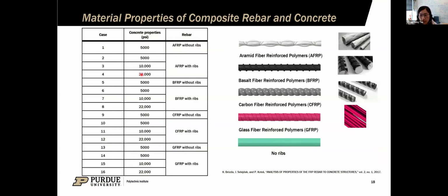So the data provided by the physical testing is limited because it takes quite a long time to do each sample experiment. So we want to use a large data set for optimization and condition assessment. We definitely need some complementary ways to generate the data. So here we develop multivariate numerical models in finite element analysis. We study the effect of 4 different composite rebars, including AFRP, BFRP, CFRP, and GFRP. We also check the effect of the concrete strength, from 5,000 all the way to 22,000 PSI. And we also check the effect of the ribs on the rebar to see if they affect the mechanical performance.